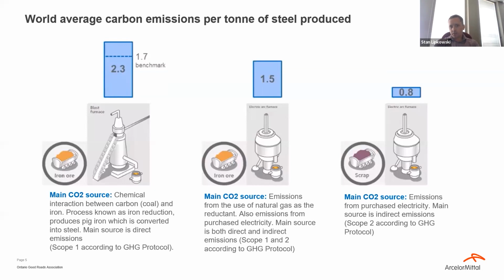Now, if you shift to the electric arc furnace technology and you feed the electric arc furnace with 100% iron ore, that drops down to 1.5 tons of CO2 per ton of crude steel produced. And then if you feed the electric arc furnace with 100% scrap, it drops down to 0.8. Now, these are global average numbers, and in some areas, the electrical grid is a lot cleaner than in others. So, for instance, if we feed 100% scrap into our EAF furnace in Quebec, where the grid is 100% decarbonized, that number will drop to 0.3. So I find it amazing that you can go from 3 on one extreme all the way to 0.3, reducing the emissions by a factor of 10 for producing the same product using technology that's readily available today.